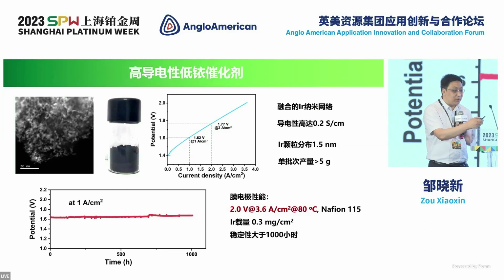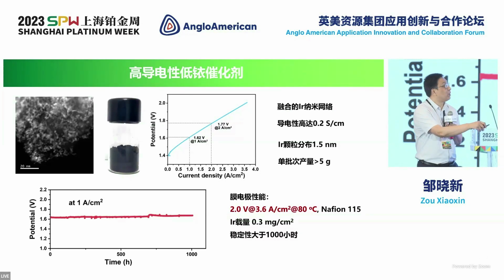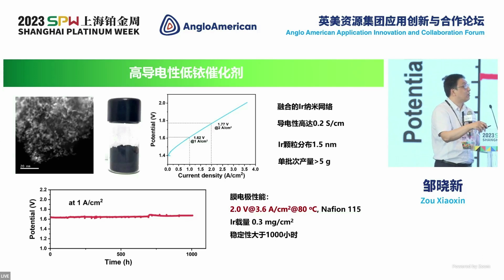So no matter how you change the structure, the capacity of the iridium has a limit. So that's why we are also developing the carrier material. No matter if it's the iridium particle or the other particles, we need to develop a carrier for improving its good features. And we can see that in the structure, the different particles are interconnected. By combining this connectivity and by producing such a carrier, we can also reduce its cost and improve its activity.